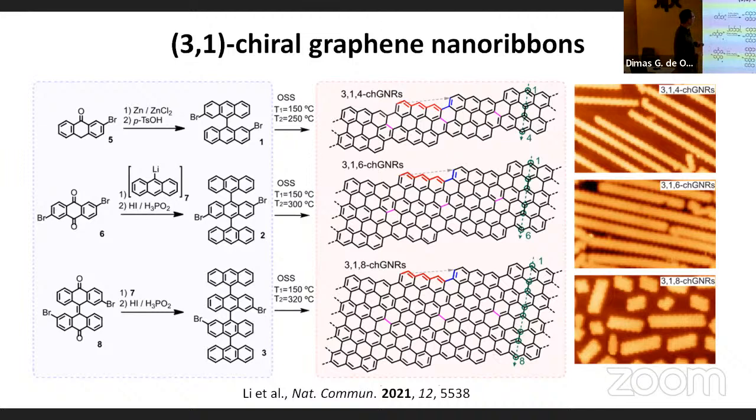The next step, once you have a polymer of these structures, is to planarize them, to get rid of these hydrogens. That's something that probably wouldn't occur in solution. Here, I think the driving force is basically that when you are on a surface, these molecules like to be planar. The interaction with the substrate is very stabilizing, and obviously they interact with the substrate more if they lie planar than if they are in a three-dimensional space. In my opinion, that is what allows these cyclodehydrogenations to occur.